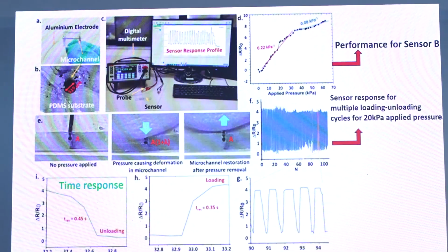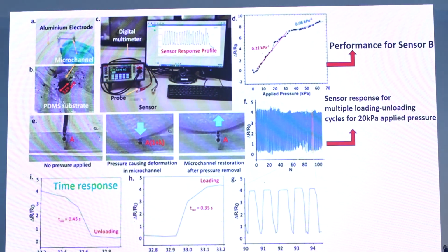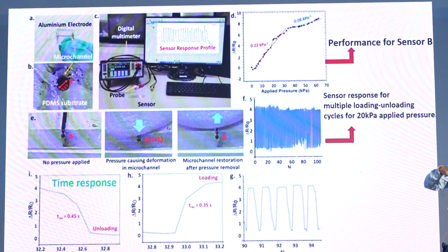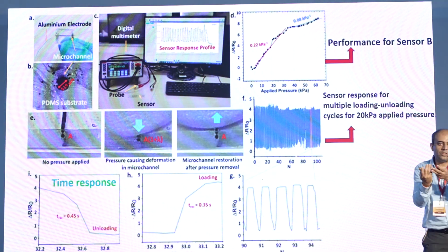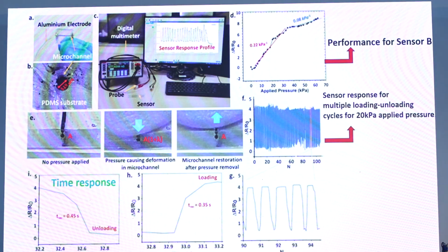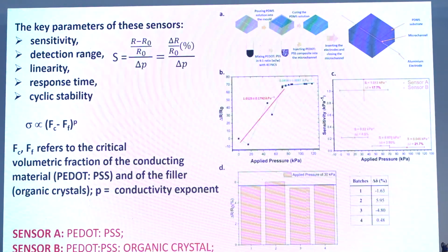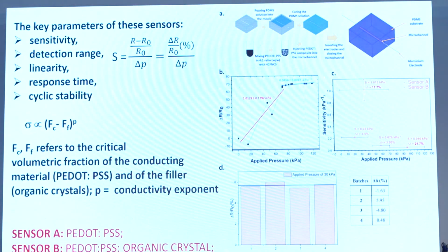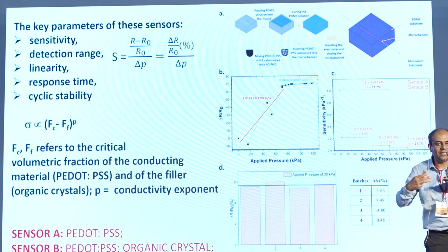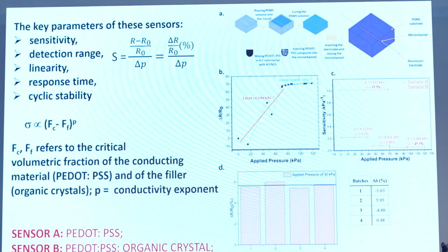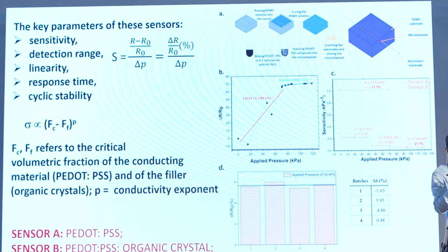But what is interesting for a sensor is a very smooth increase in sensitivity as a function of pressure. Normally there are abrupt discontinuities, and also when you withdraw the pressure, whether the device comes back to the initial state. If you look at this one, which is without my material, it's not a reversible process. It is a discontinuous process with instability. I'm not able to get data points across the entire spectrum of pressure. Now I create that stability by putting in this mechanically compliant crystal, which accommodates the pressure applied on the sensor so as to monitor the electrical responses more accurately.